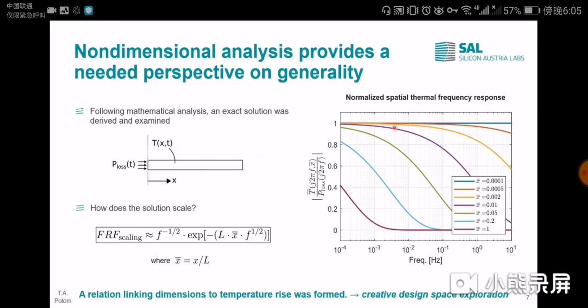Ultimately, we derive in the paper a normalized spatial thermal frequency response, which shows that the normalized temperature rise at the boundary where the losses are is significantly higher than on the tip of the domain, which matches our intuition. We also derive a scaling solution which describes how the frequency response function magnitude is a function of the harmonic loss dissipation on the boundary and also as a function of the spatial domain variable.